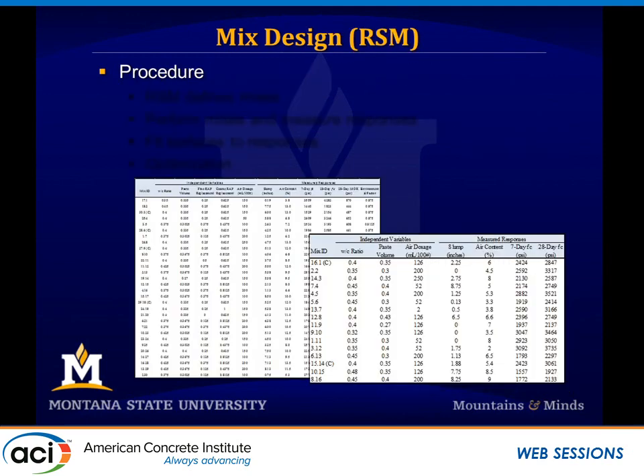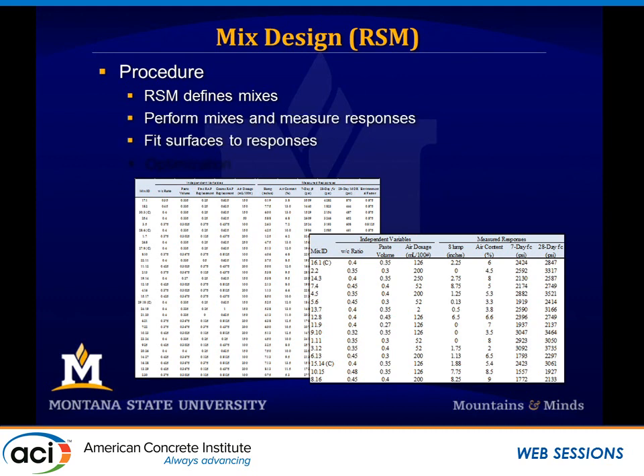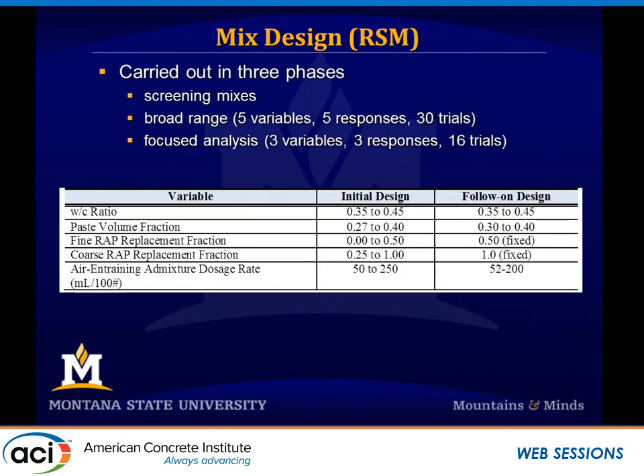to optimize our mixes. So the way the procedure works is you go into response surface methodology and you say, hey, these are my variables and these are the ranges of my variables. And then the response surface methodology says, great, do these mixes. Okay. You then perform those mixes and then measure the responses. Once you get those responses, you then plug them back into the response surface methodology, and it fits some surfaces to it. And this step is regression. It just fits equations to your responses and applies a bunch of statistics stuff that I don't quite understand fully at this time. But then it outputs these surfaces and confidence in those surfaces, and then you can use that for optimization. That's kind of the process used.